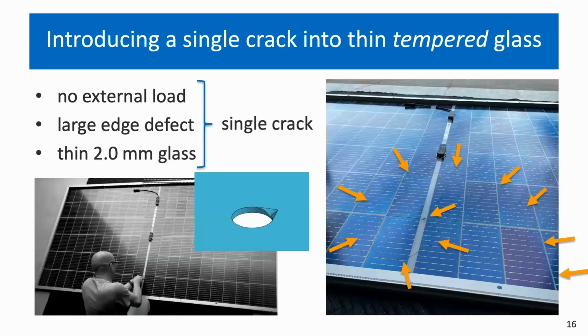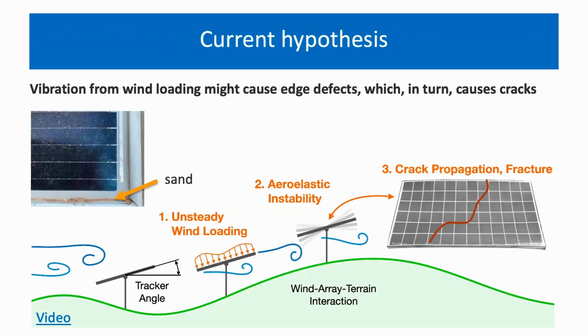However, if we experimented a little more with it, we have here an unloaded PV module. And on the back here are so-called junction boxes, where the cables are coming out. We removed one of those and put a big notch into it with the file that's shown here. And then we got a spiral-forming crack. And remember, this is in a glass that has a compressive stress similar to tempered glass, where you would actually expect it to shatter into a lot of pieces. Whereas here we just get one single crack. And so this is where we're at currently.